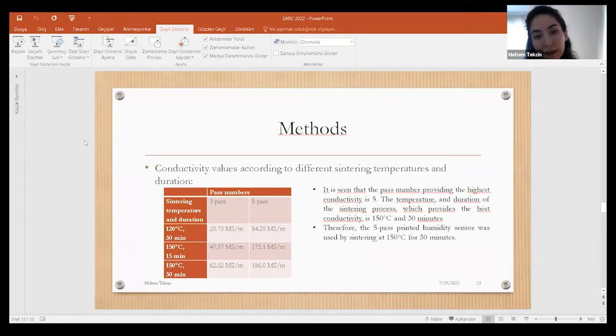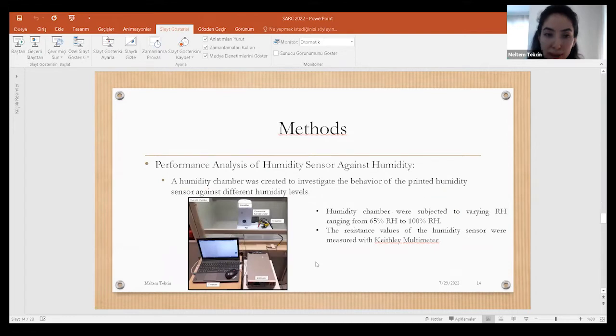According to the table, it is seen that the pass number providing the highest conductivity is 5. The temperature and duration of the sintering process which provides the best conductivity is 150 degrees and 30 minutes. Therefore, the 5-pass printed humidity sensor sintered at 150 degrees for 30 minutes was used.